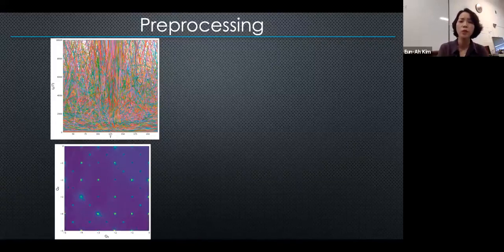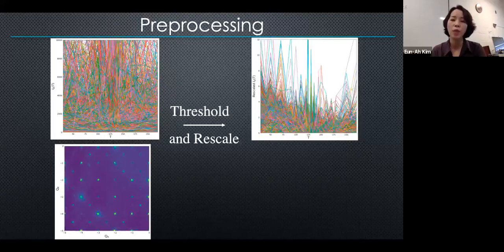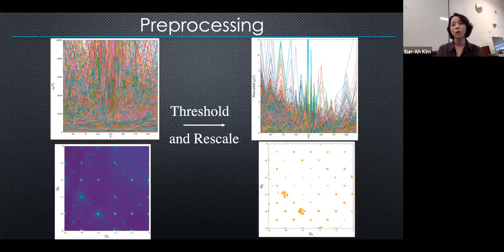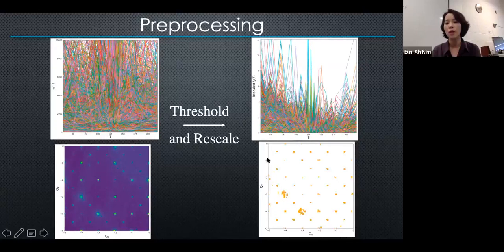So some information that's staying more or less low at all temperatures is obviously not of interest to us. Another issue is if you look at the entire momentum space and put a grid and try to keep track of each Q, a large part of the momentum space, such as this area here, actually does not have much intensity. So it's very sparsely distributed. We deal with both of these issues by thresholding and rescaling. We threshold based on the average over the entire temperature range and only keep the data that have significant average, with a well thought through thresholding scheme. And after the thresholding, what we're left with is only these Q points to consider as our population to think about.